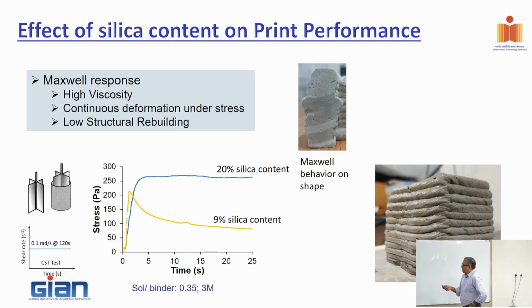Right. So this is what would happen. So 9% silica, 20% silica. 20% silica is showing you the Maxwell behavior. Look at this. Right? The 9% is showing a yield type behavior. This is what you get. Look, the layer definition with 9% silica looks okay. But when you look at the 20% silica, you see the layer deformation here. It's basically starting to spread out.